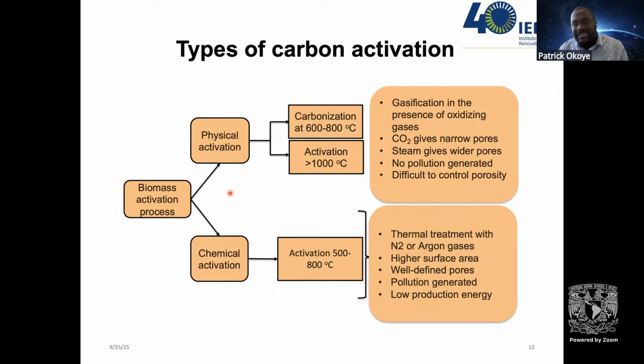But one of the challenges is that after production, with chemical activation, you have to wash several times to ensure that excess salts, acid, or the chemical agents used are actually removed from the activated carbon. This is because activated carbon for use has a regulation. So it does have limits on the number of foreign elements, whether alkaline or heavy metals, that should be there before it can be used. Otherwise, we are going to be causing pollution downstream.